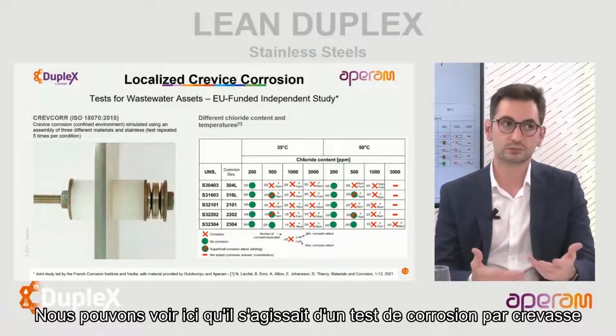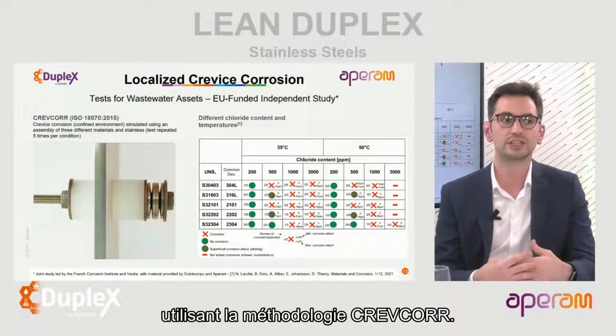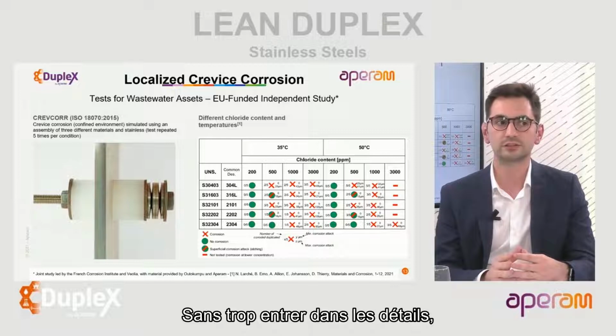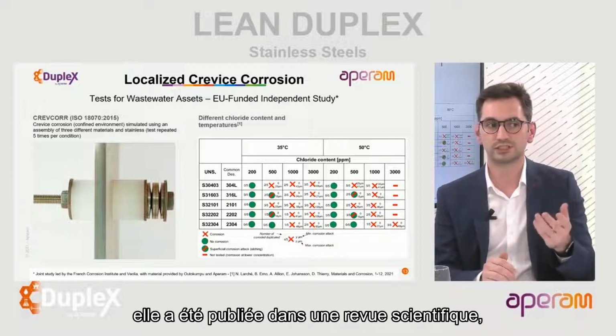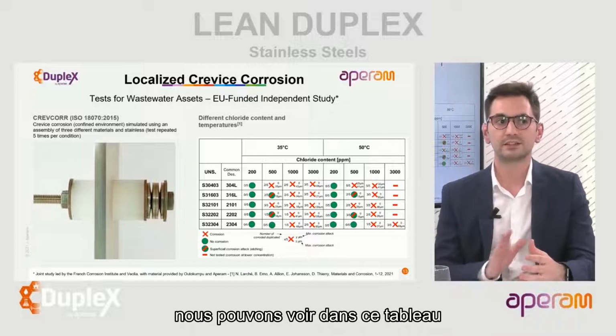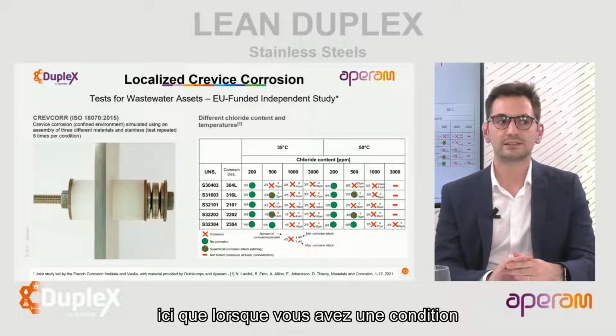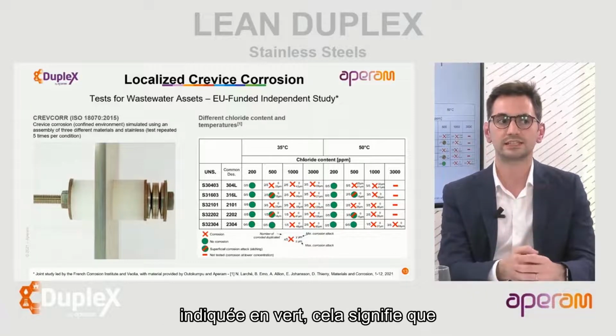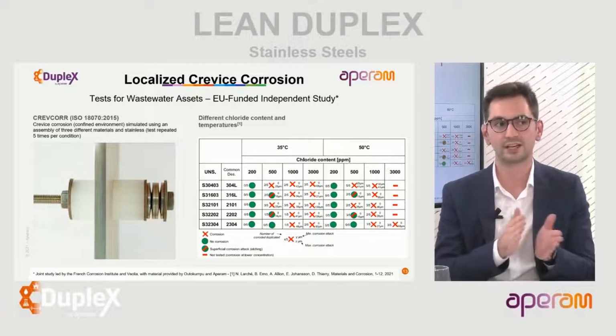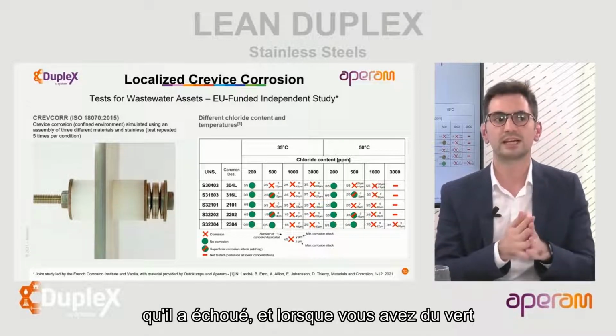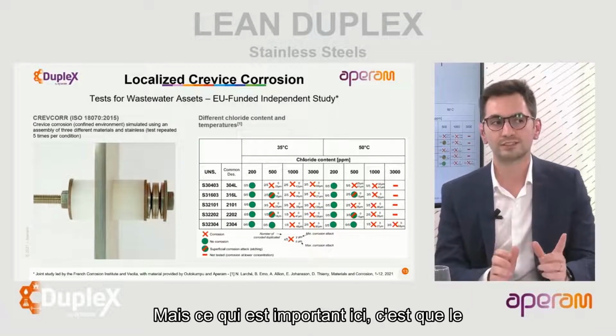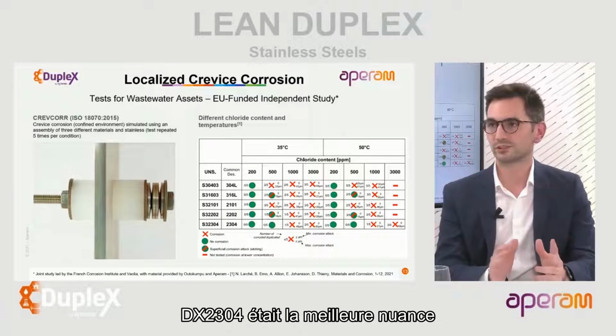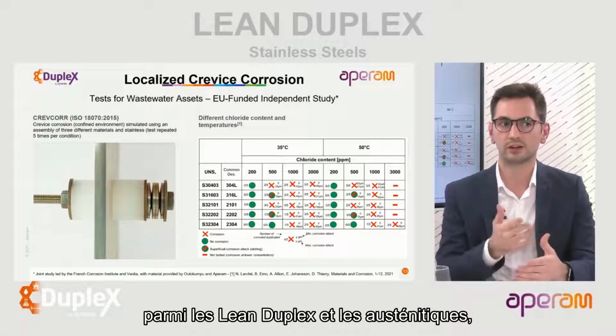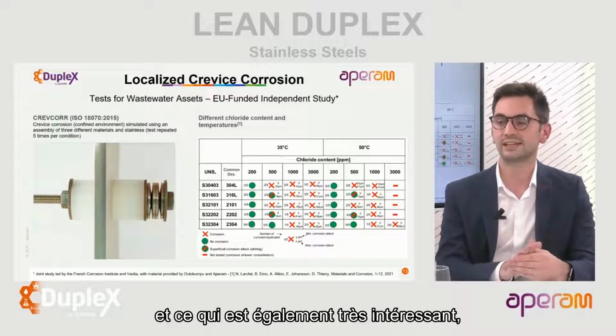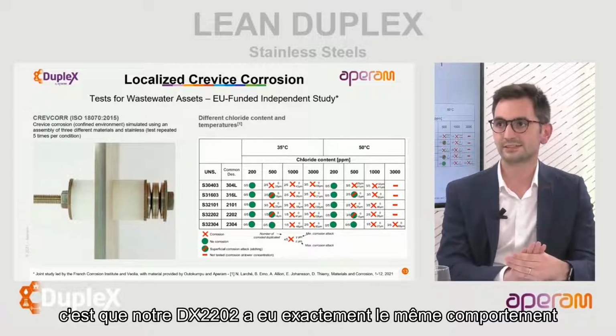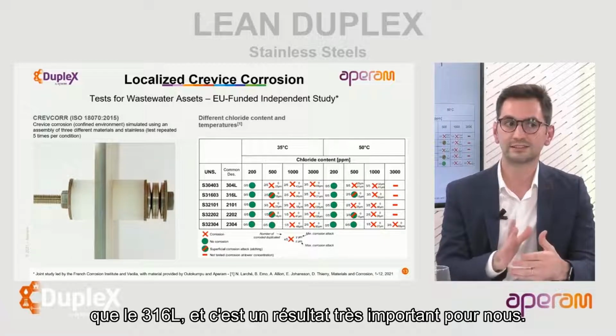We can see here it was the crevice corrosion test using the CREVCORR methodology. And without going too much into detail, because this study is public, it was published in a scientific journal, we can see in this table here that when you have a condition indicated in green, it means that that steel passed the test. When you have a red cross, it means that it failed. And when you have green and red, it partially passed. But what is important here is that the 2304 was the best grade among the Lean Duplexes and austenitics. And also very interesting is that our DX2202 had exactly the same behavior as the 316L. And that's a very important result for us.